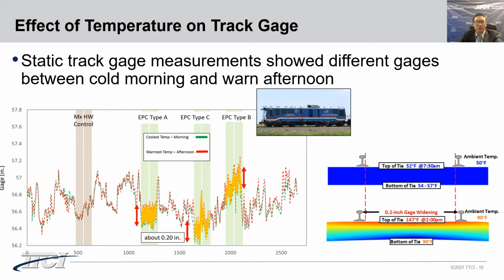Three composite tie test zones had about 0.2 inch gauge widening due to thermal effect. The drawing on the right shows the general observation that the bottom of the tie tends to remain insulated by the crib ballast. This behavior creates a thermal gradient and generates a center negative bending. Linear expansion of the tie coupled with this bending resulted in a 0.2 inch gauge widening, consistent between all three composite tie zones. No measurable gauge increase was observed in adjacent wood or concrete tie test zones throughout the day.